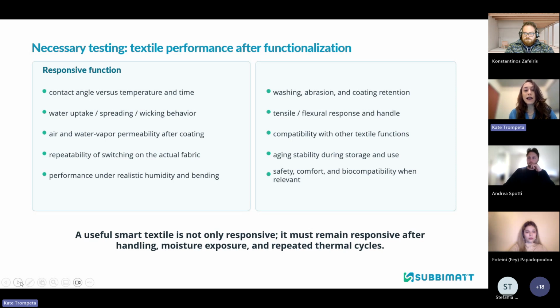A useful smart textile is not only responsive, it must remain responsive after handling, moisture exposure, and repeated thermal cycles. That's why we need to fulfill the performance and the functionality, but of course, to withstand washing, abrasion, and to check the coating retention, also to have tensile and flexural response during handling, compatibility with other textile functions, also to ensure that the aging stability during storage and use can be fulfilled, and of course to fulfill the safety, comfort, and biocompatibility when this is relevant.